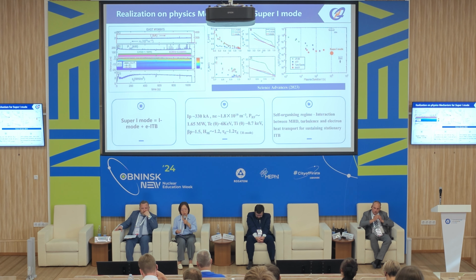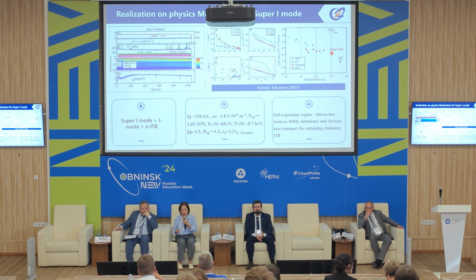And also it's very interesting, we call it super I mode because it is I mode combined with the ITB dominated by the electron heating. So from the electron temperature profile, we can see there's a strong ITB in the core. Here I list all of the parameters. And by this experiment, we find this is a very interesting self-organizing regime. A good interaction between MHD, turbulence, and electron heat transport, so that the stationary ITB can be sustained during the long-pulse operation. And this result has also been published in a journal last year.